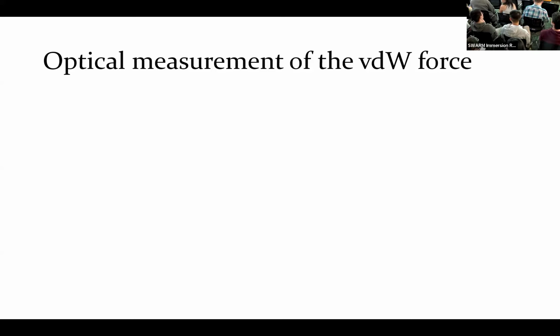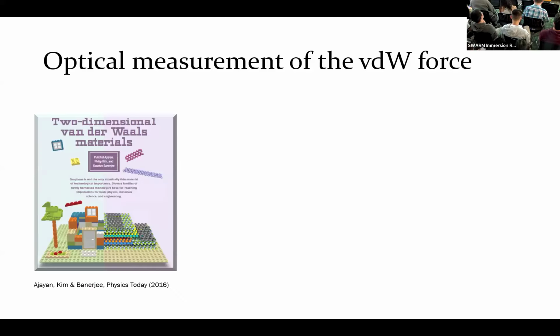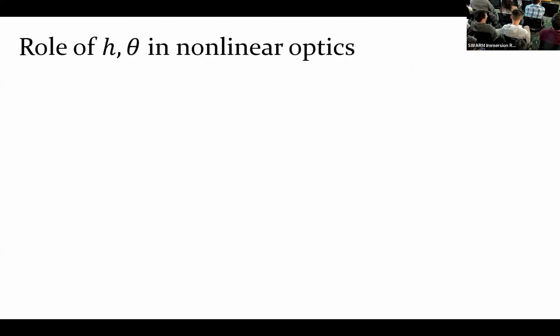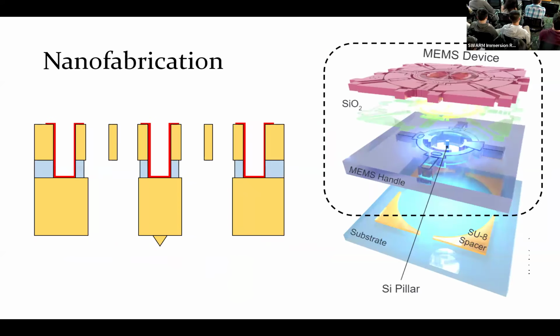The question is how do we make sure the two layers of 2D material are parallel to each other? 2D materials are intrinsically flat, atomically flat. So the only thing we want to make sure is that the bottom of the silicon pyramid is flat with respect to the substrate. The 2D materials themselves we just assume to be flat because they are supposed to be flat. There are two aspects to this. First, the pyramid has to be flat with respect to the MEMS chip itself, and that's usually easy to guarantee because these are etched by KOH. If you have a uniform etch rate, then the top of the pyramid is flat with the rest of the chip.